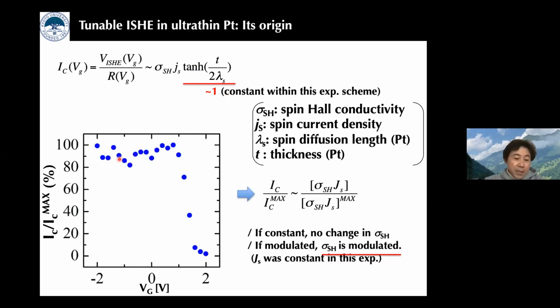Next, we plotted the gate dependence of the normalized electric current, shown here. If the normalized electric current is not gate dependent, this means the spin Hall conductivity is not gate dependent, because the spin current density is not gate dependent in our experimental scheme. But the reality is not so. As you see, the normalized electric current is largely modulated by the gate voltages. This means the spin Hall conductivity is modulated by the gating.